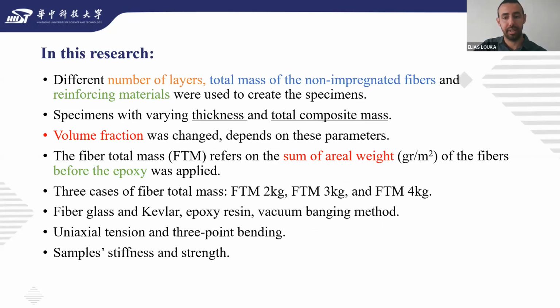The fiber total mass refers to the sum of areal weight of the fibers before the epoxy was applied. 3 cases of fiber total mass were used, masses of 2, 3, and 4 kg, with different number of layers, which depends on the areal weight of the specific material. Specimens of fiberglass and Kevlar were prepared using the vacuum bagging method. We used epoxy resin as the matrix material. The mechanical behavior of the specimen were tested under uniaxial tension and 3-point bending. Specifically, we examined the sample stiffness and strength.